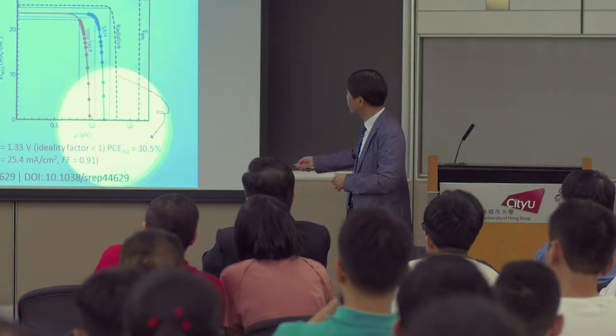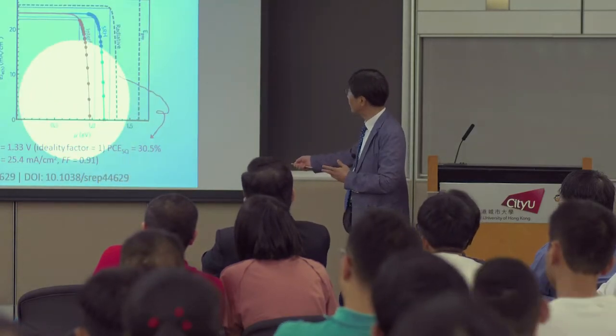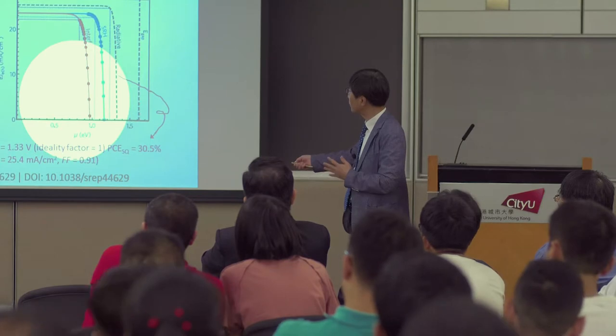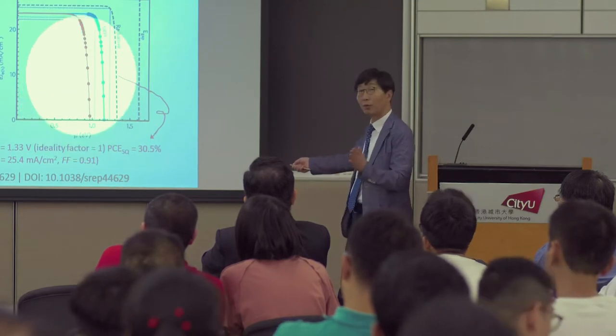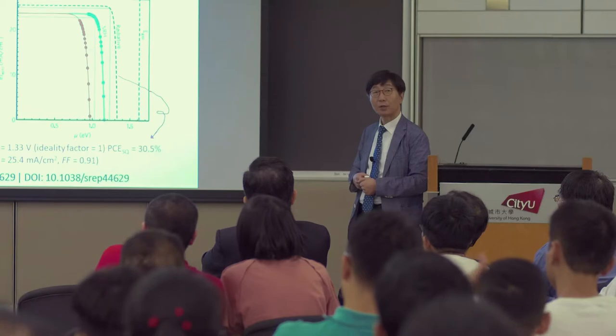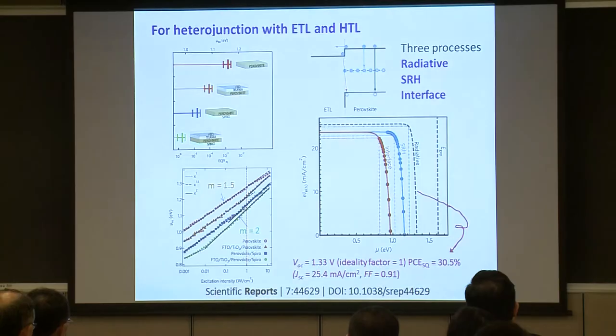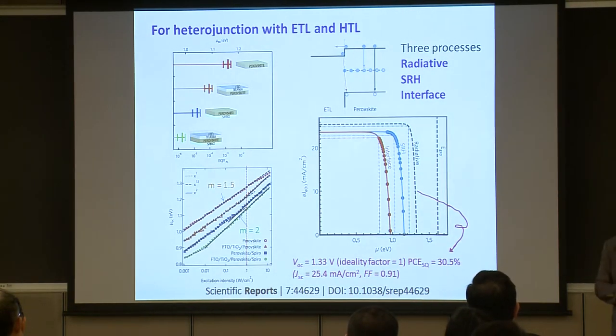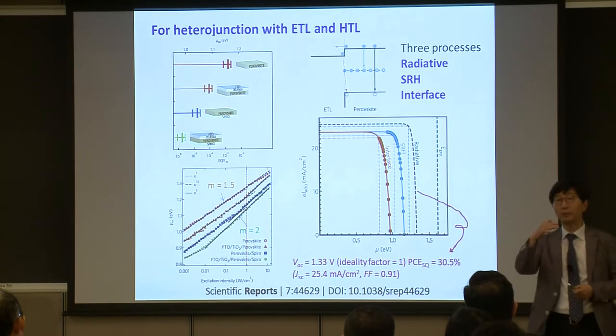And sometimes you found that the open circuit voltage is even lower than 1.0 volt, or close to 1.0 volt, without changing the short circuit photocurrent density, which is indicative of the interface engineering. So interface is very important.